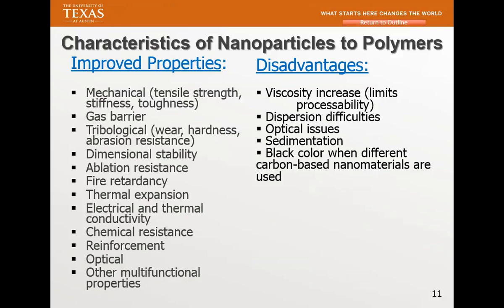Another area is what you call disadvantages. Most important one is viscosity increase, especially when you work with thermoset. You put a little bit of nanomaterials in there, your thermoset is so viscous, if you're using it as a resin and put it in the fiber, you cannot process it. Then you lost the processability. And you may say, I have a very good nanocomposite, but I cannot process anything. Well, that's useless. So you really need to think about viscosity.